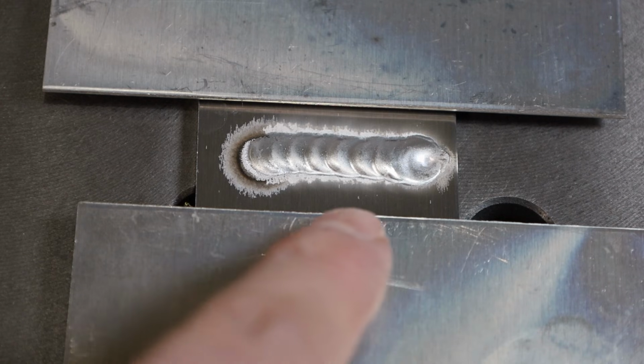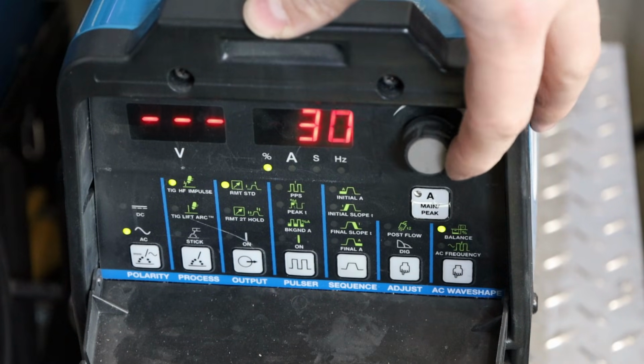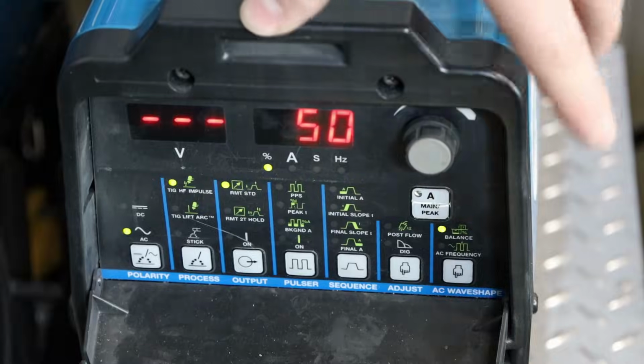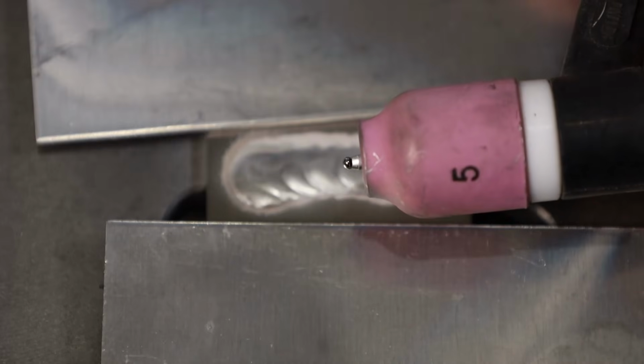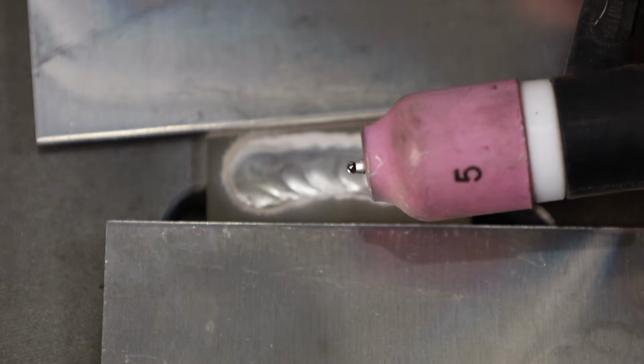On the other hand, here I've turned the balance way down to 50%, and while this camera view doesn't let you see the tungsten balling up, it is, and you can see there's more light emitted as the arc length is getting long, and it's really out of control. I'm not able to maintain the technique that I need, and so I didn't get a good result there either. So those are some of the signs to look for when it comes to AC balance, to know that you have it set right. Now that we've gone over the settings on the machine, I think you should be able to have things set well enough to get going, right?